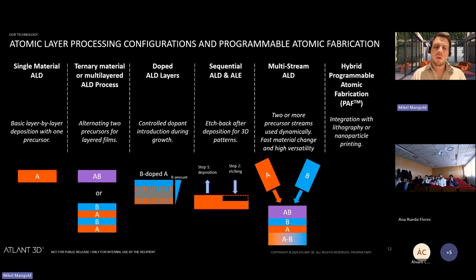Because we can control the different materials, you can create doping layers and fully control the stoichiometry. That is also something almost not feasible before. So that's what we can do. We can stack material and dope material, and control that with predictability.